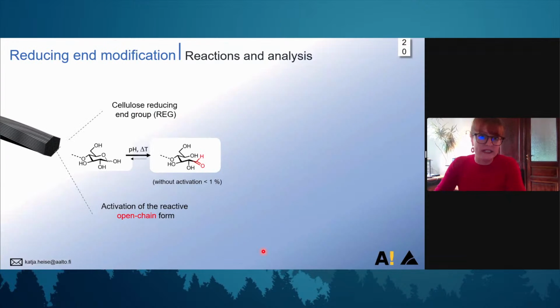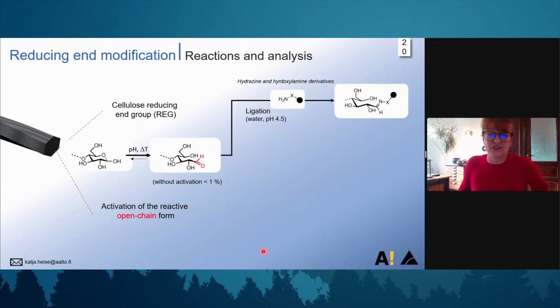Okay, so this is something you have seen before. We have our cellulose nanocrystals with reducing end groups pointing to one side. These are in equilibrium with our hemiacetals. So what we need is either acidic or basic pH or high temperatures in the presence of water to really activate the ring opening. And then we use aldehyde-specific chemistry. So the chemistry we can use is, for example, a ligation reaction.